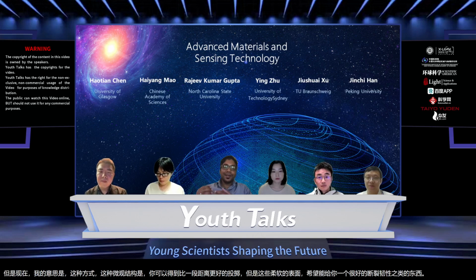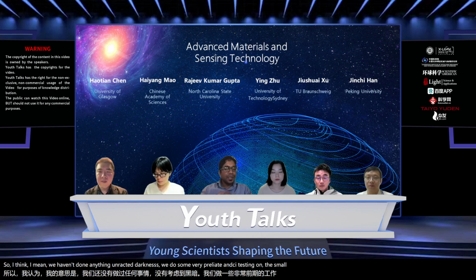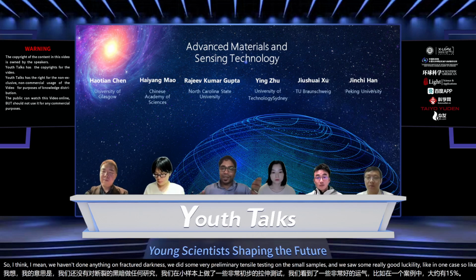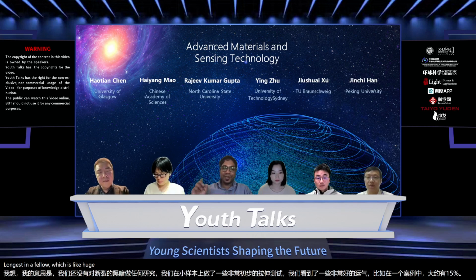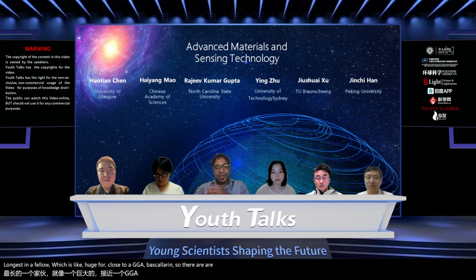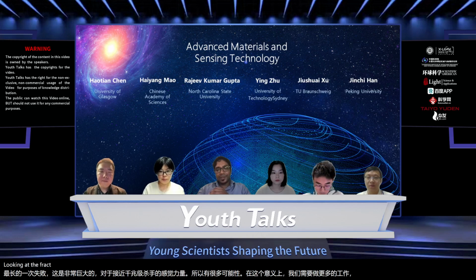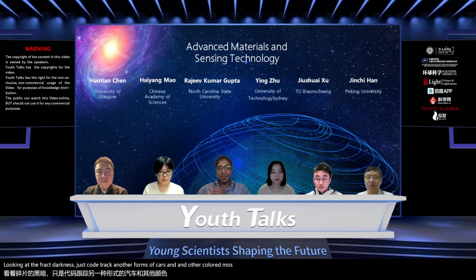So we haven't done anything on fracture toughness. We did some very preliminary tensile testing on small samples, and we saw some really good ductility. In one case, 15% elongation at failure, which is really huge for close to a gigapascal of yield strength. So there are lots of possibilities. We need to do a lot more work in that sense. And looking at fracture toughness, stress corrosion cracking, and other forms of corrosion and other failure modes is super important.